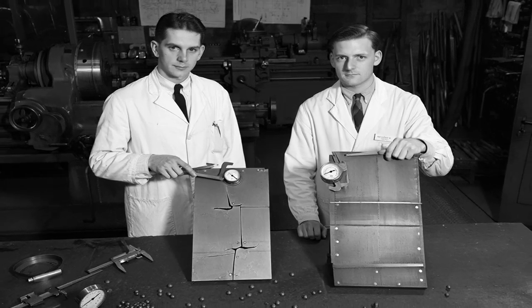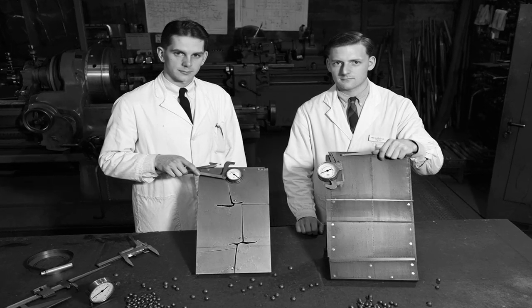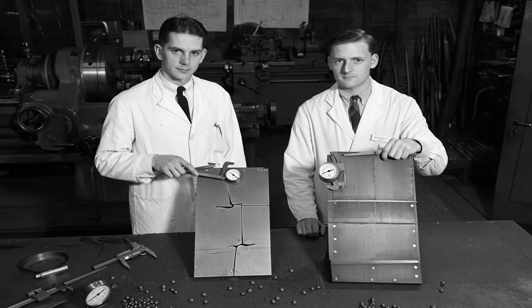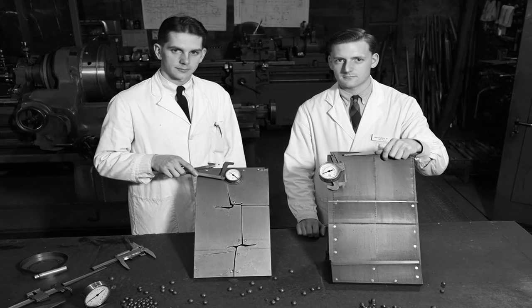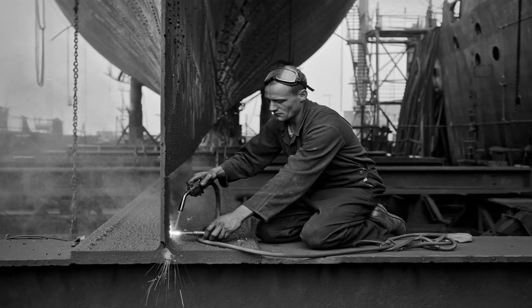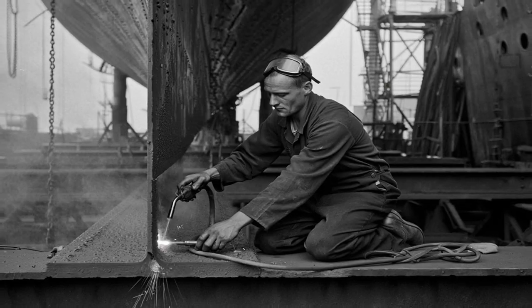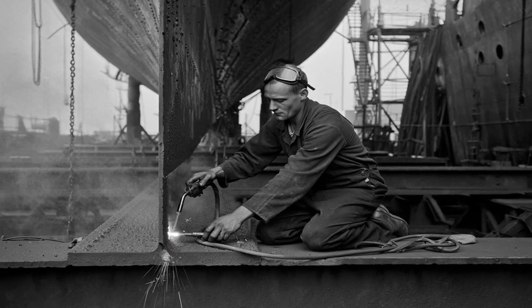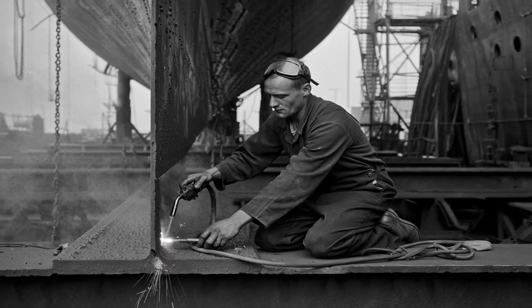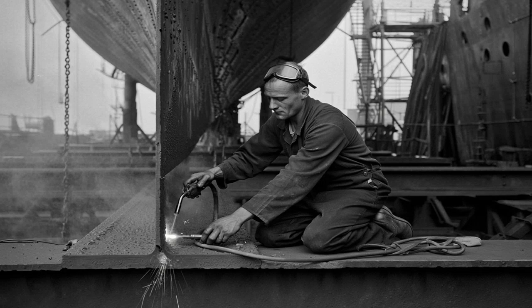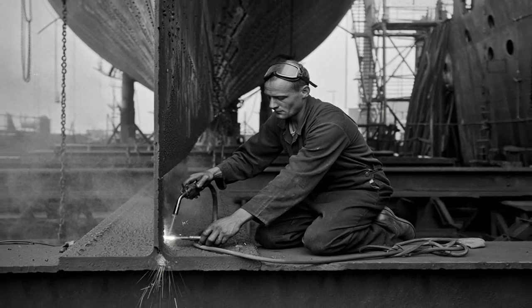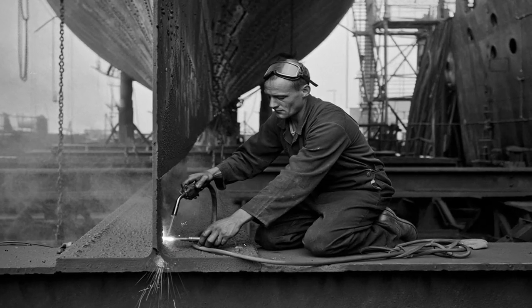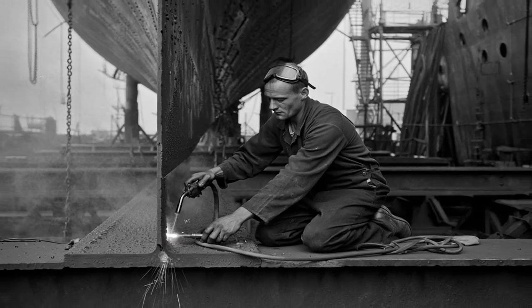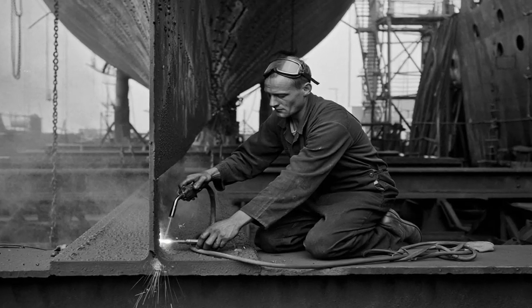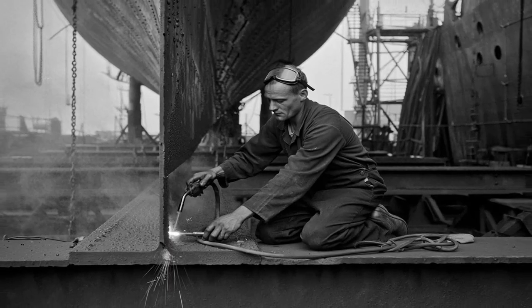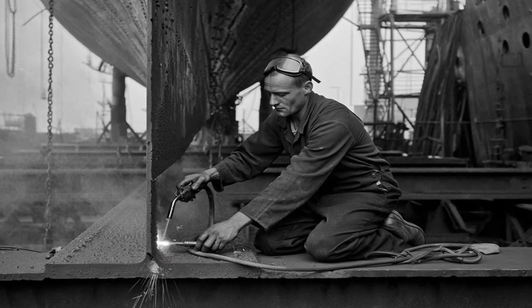The base metal remained the same. The joints showed no chemical variances. Solely the sequence of steps differed, but the overall durability leaped ahead in ways the specialists at first dismissed as implausible. The mechanics of the breakdowns at last came into focus. Steel isn't an inert substance. It forms a crystalline lattice that reacts vividly to thermal shifts. When fabricators guide a flame across a joint, they generate a hot spot surpassing 2,500 degrees. The material swells sharply in that localized area. During cool down, it shrinks, yet the adjacent cooler sections resist this pullback. This leaves enduring pulling forces embedded in the framework, persisting unless the welding pattern permits their even dispersal.